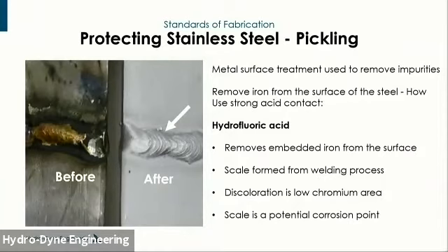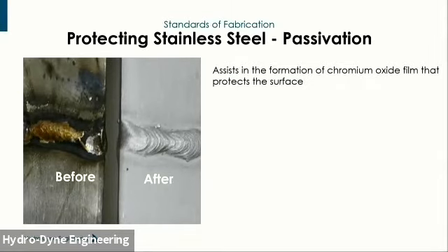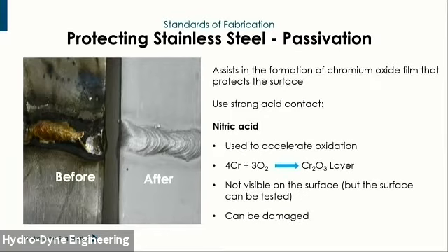After contact with hydrofluoric acid, we get a very clean surface, which then we can use on the next process for surface treatment, which is passivation. So we passivate all the steel. This assists in the formation of a chromium oxide layer that protects the surface. So we use strong acid contact for that as well with nitric acid. So that's used to accelerate the oxidation of the surface layer of the steel. It's not visible on the surface, but we can test to make sure it's there. The oxidation layer is nanometers thick, and it can be damaged. So after we take the time to clean the steel and passivate it, we have to be very careful that we don't damage the surface.